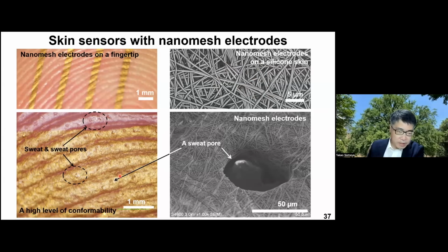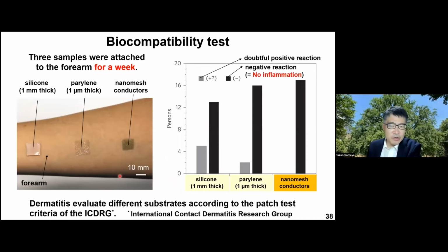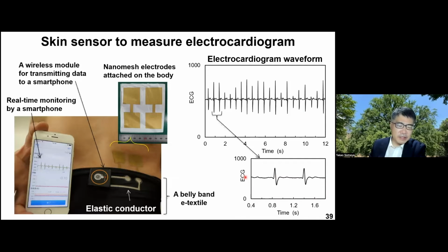If we look at the sweat pore region carefully, sweat is penetrating from the sweat pores. Such breathability, or natural penetration and vaporization of sweat, is very important to ensure biocompatibility. Indeed, when nanomesh conductors are attached to people's forearms continuously for a week, none of the participants show any inflammatory issues, while 1 millimeter silicone and 1 micron thick parylene, both known as non-toxic and biocompatible materials, exhibit a fairly large risk of inflammation. In that way, we eventually realized breathability is quite important to enhance biocompatibility.